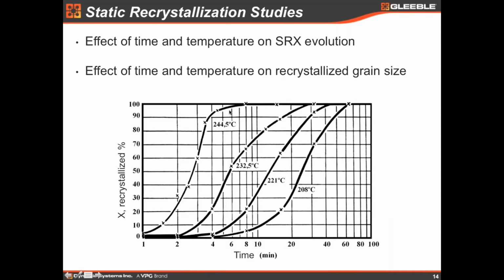So I'd like to give some ideas. Yeah, I have this figure again. We can study the effect of time and temperature on the recrystallization evolution, and the time and temperature on recrystallization grain size. So it's a very simple experiment. I have a work hardened specimen, and I mount that into the Gleeble, and then I program this time, let's say 1.5 seconds at this temperature, and then this time again at this temperature, and several times.